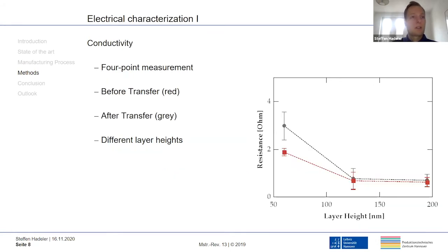Following the material characterization, an electrical characterization was carried out. In a 4-point measurement, the conductivity of the coating before and after the transfer to the PDMS was evaluated in different layer heights. It should be investigated whether the transfer has an influence on the conductivity, and whether the layer height has an influence on it.